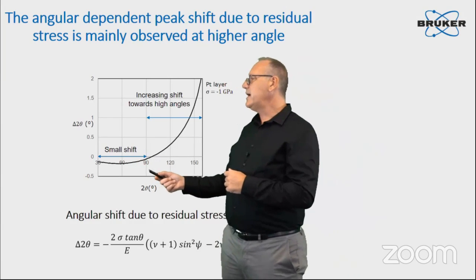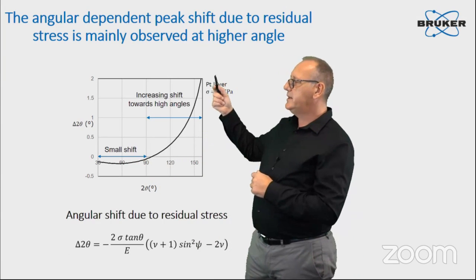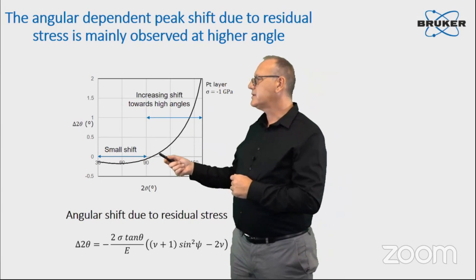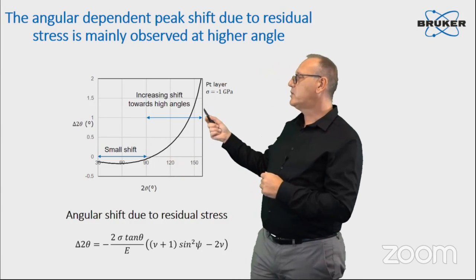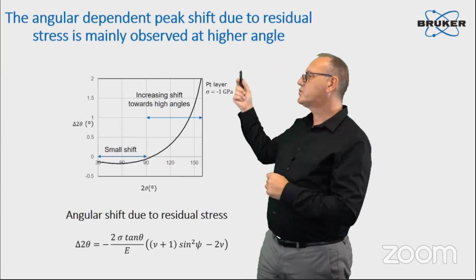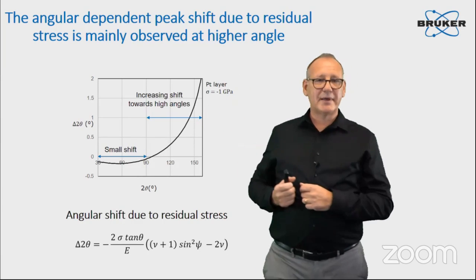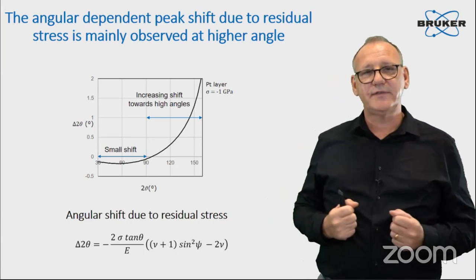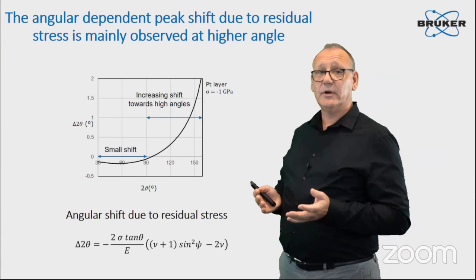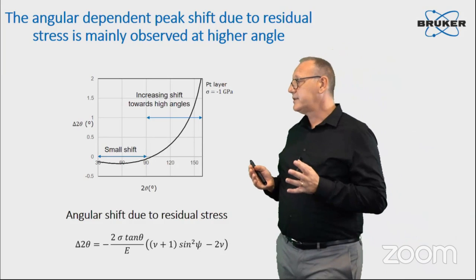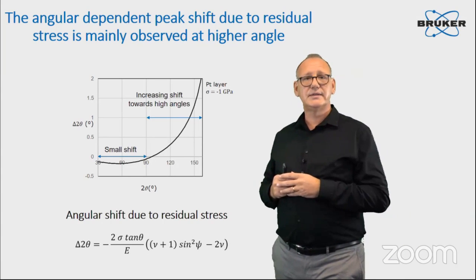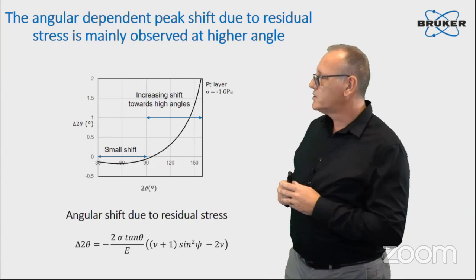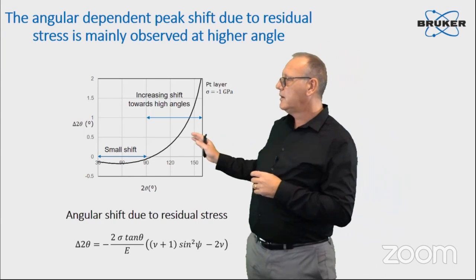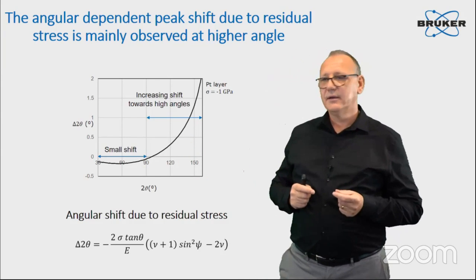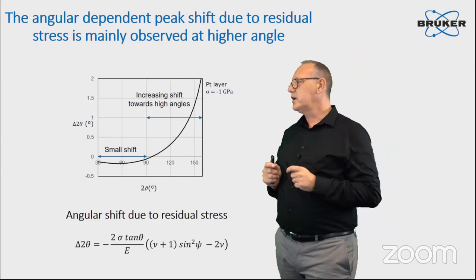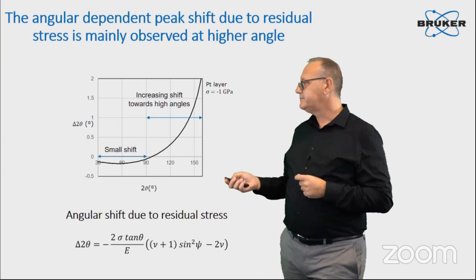If you scan at higher angle, you see how tremendously the shift acts on the peak position. Here we took a calculation for a stress layer of 1 gigapascal, so 1000 megapascal compressive stress. That seems to be a big number, but that's not, that can often be the case in very thin layers. So you see here, by measuring at high angle, we have actually identified something we would not have seen by scanning at low angle.